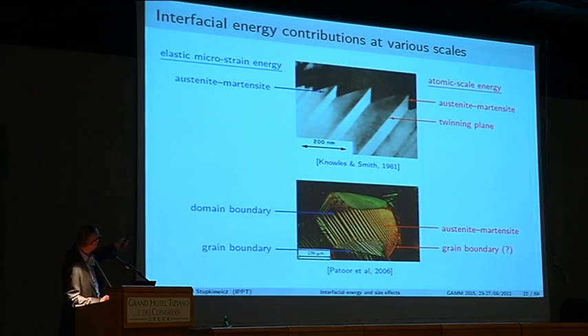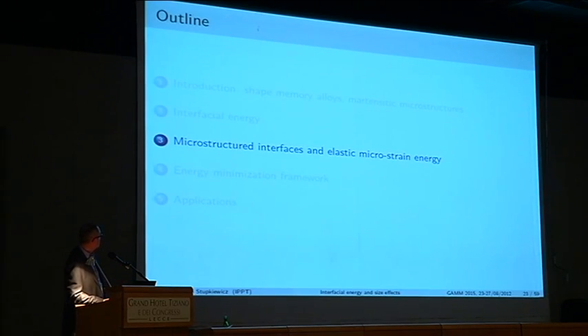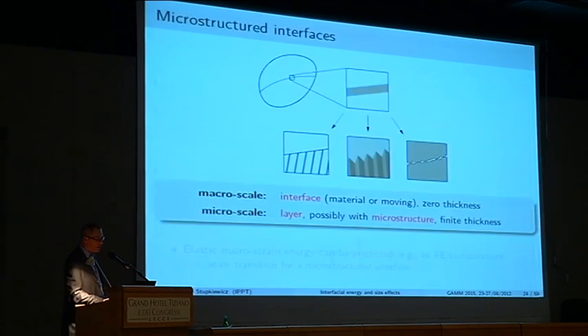And then we have the elastic microstrain energy on the left side. So this one we discussed, but we also have energy of this kind at other interfaces. So at the grain boundaries, we have martensitic plates terminating at the grain boundary. This is exactly the same kind of elastic strain energy there. And also we have domains, and again at the boundaries of these domains of individual laminates, we also expect energy of that kind. So these are all the kinds that one might be interested in to consider and to include in the modeling. And this brings me to the concept of microstructure interfaces.